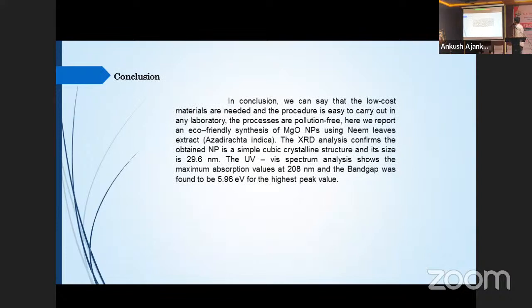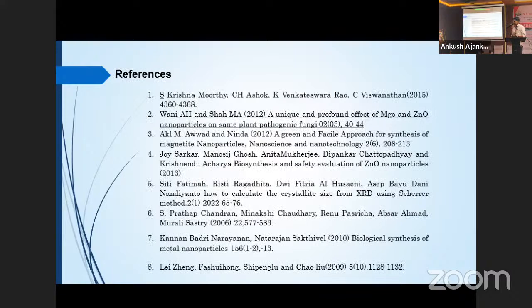Conclusion. In conclusion, we have seen that low-cost materials are needed and the procedure is easy to carry out in any laboratory. The process is pollution free and eco-friendly, for the synthesis of magnesium oxide nanoparticles using neem leaves extract. The nanoparticle size is 29.6 nanometers and the energy band gap is 5.96 electron volts. Next slide. These are the references. Next slide.